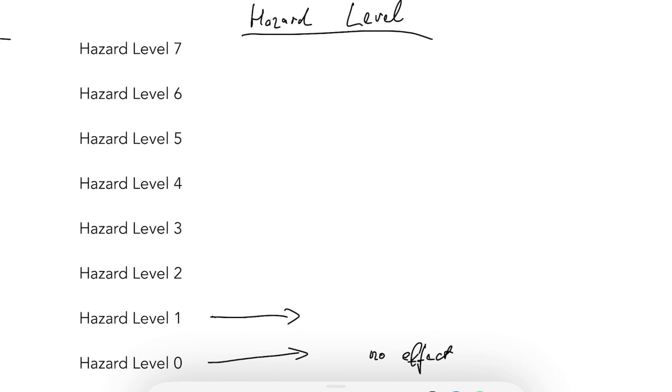I mean, it's not really a defect. It says passive protection device is activated. Passive protection means it's not the BMS. The BMS would be an active protection device that notices, oh, the cell went over voltage, I need to switch off the battery. But it means there is some element inside the cell that stops the reaction, for example, stops the operation, stops the current, and shuts down the cell and brings it into a good state. For example, a CID would be such a thing.